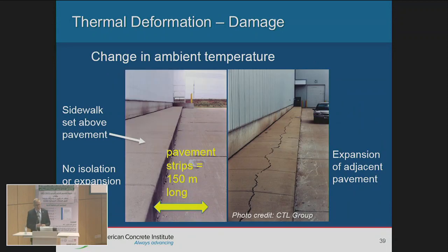Also, we talk about ambient temperature. If you look at the picture here on the left, that was built with no joints. Here you have that one slab that continues for about 150 meters long with no joint. And they built then this curb on top of it, which acts as a restrainer. Many years later, if you see now that structure, we have a crack in the curb, because again, the concrete wants to move. And it finds a way where it would crack.